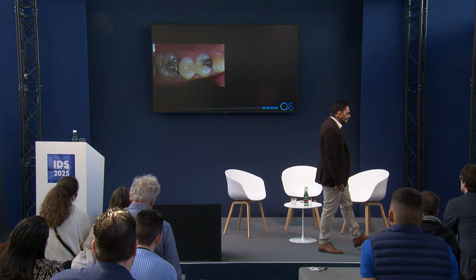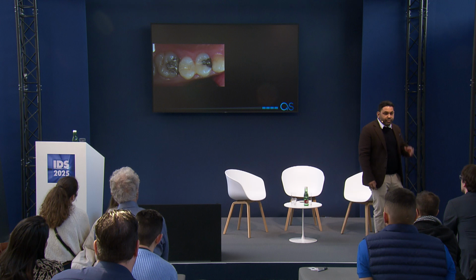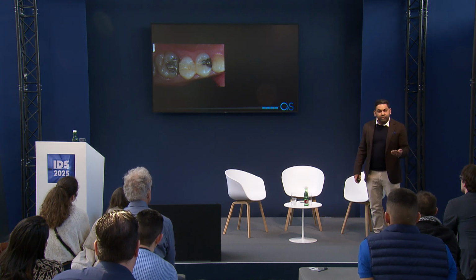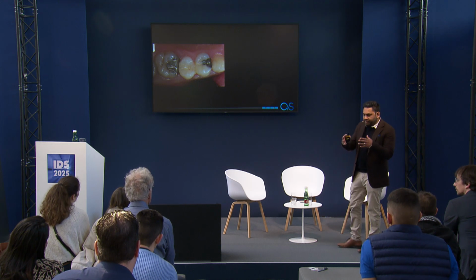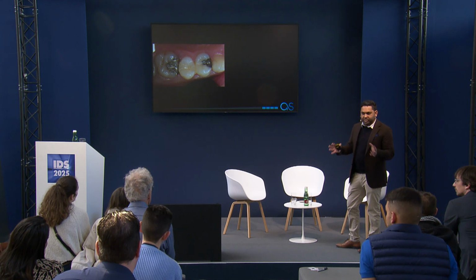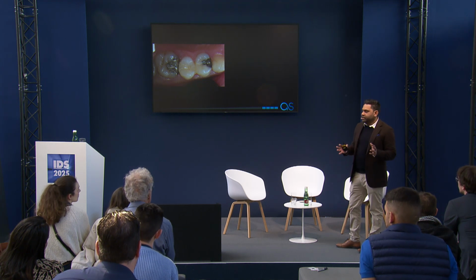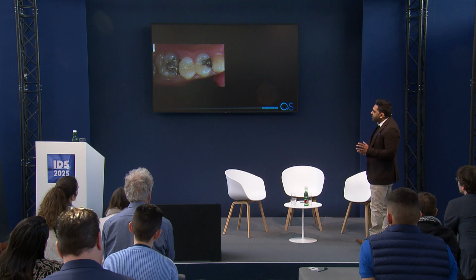So I also wanted to test the limits of the material to some degree, in terms of aesthetics. A challenging situation is when we're replacing failing amalgam restorations. Often we get the leaching of the amalgam on the surrounding substrate, so the substrate can be quite dark. So how did the material perform there?